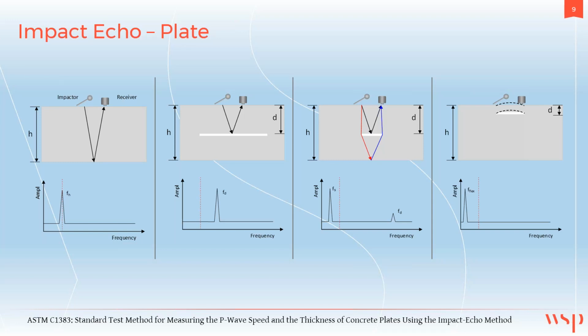Another phenomena for very shallow defects is that the defect as a whole can vibrate in a way that's referred to as a drumhead effect. That results, rather than a very high frequency response, in a low frequency associated with the vibration of the delaminated element above the very shallow defect. So it's important to understand where these different responses may influence the feedback that you're seeing.